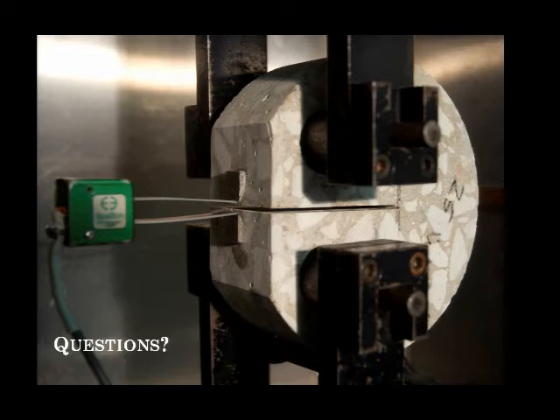What if you measure the LLD in that beam test? The problem with that is, if we take it directly from the LVDT of the actuator, there's stiffness issues in the actuator itself that would crop up in that data. We could try, I guess, to place a neutral axis LVDT on there. I never thought about that. People have done that? Okay, and they saw no major change.